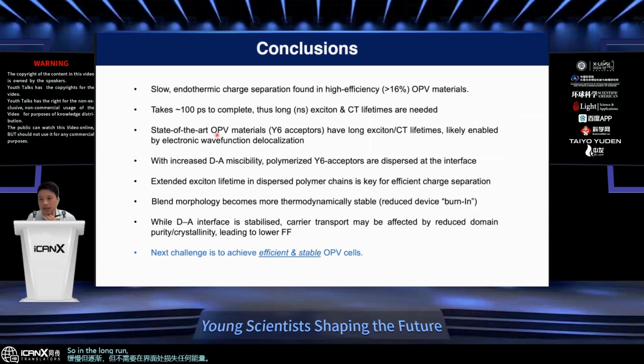So in the long run, this is why we now have more efficient systems. But then we now have the stability issue that we need to solve together. And we need to find a way to both stabilize the donor-acceptor interface and the overall morphology, but at the same time without compromising the charge transport, due to the reduced purity of the domains and the crystallinity.